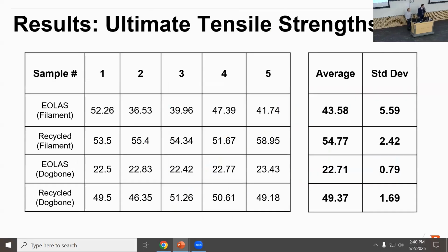And by calculating all of these values and individually charting them for the 5, we were able to get an average and a standard deviation just to see how strong they pretty much are and how consistent the data was. What we found was that in general for the dog bone, the highest standard deviation was 1.69, not that high, pretty consistent data. And the recycled dog bones,